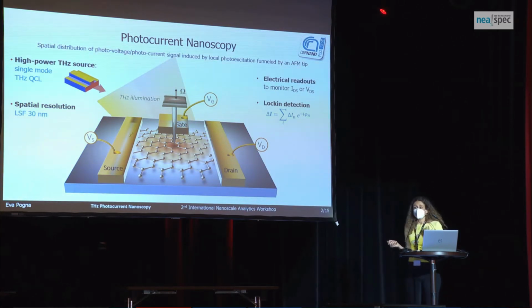And with this technique, we can achieve a spatial resolution in measuring the photocurrents and photovoltage of about tens of nanometers, which in the terahertz range is incredible. It corresponds to a fraction of 1/1000 of the incident electromagnetic radiation wavelength. To perform these measurements, of course, you need to have electrical readouts. And by exploiting the tapping operation of the NeoSNOM, we can isolate the near-field contribution to the conduction by demodulating the electrical signal at the harmonics of the tapping frequency.